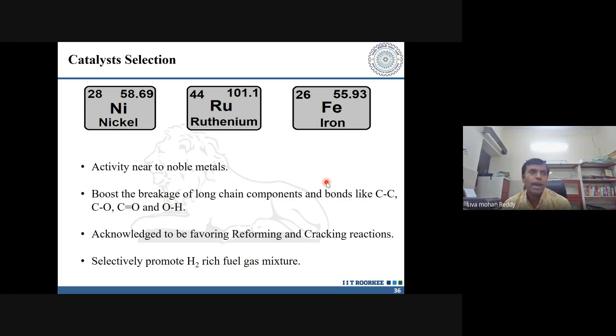And iron has a high activity for ring opening of things, like the tar components that we are talking about, right? Those are nothing but your phenolic components, which are ring shaped components. So these ring shaped components are going to be effectively cleaved in the presence of iron. So that's the reason why we have chosen these three catalysts, where these metals can effectively promote the hydrogen gas selectively via reforming and cracking reactions.